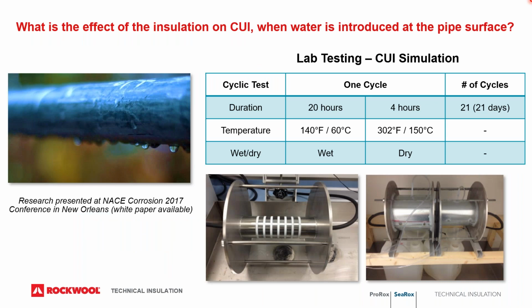Rockwool went about trying to test out this NACE statement by performing a couple of standardized tests. The first test we looked at was investigating dry out times and their relation to corrosion. We used the ASTM G189 test, which is the standard guide for laboratory simulation of CUI, and this test uses a heated stainless steel pipe with insulation and full cladding. As you can see in the photos on the bottom right, this test injects water through the cladding and insulation right to the pipe surface, and this simulates a hole or a crack within the insulation system.